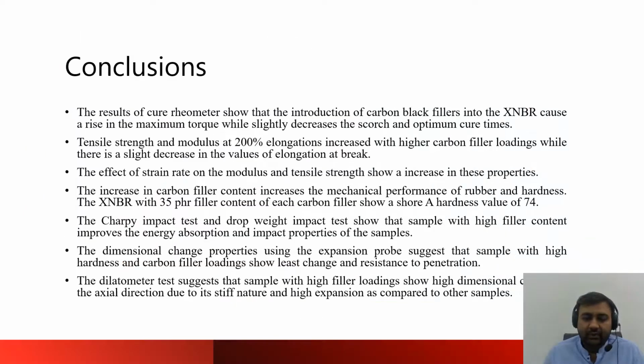So in this slide, I will be providing the concluding remarks. The results from the cure rheometer show that the introduction of carbon fillers into the XNBR causes a rise in the maximum torque while slightly decreasing the scorch and optimum cure times. The tensile strength and modulus at 200% elongation increase with higher carbon filler loadings, while there is a slight decrease in the value of elongation at break.